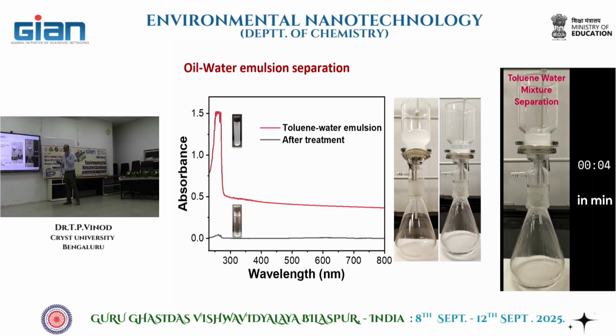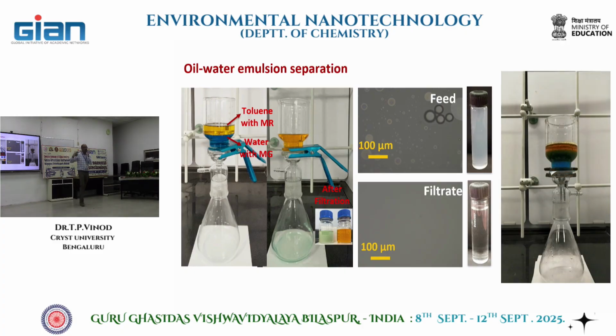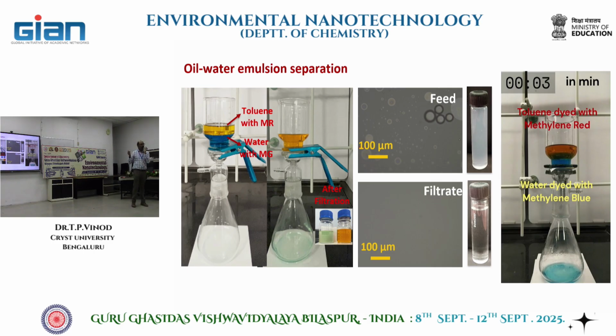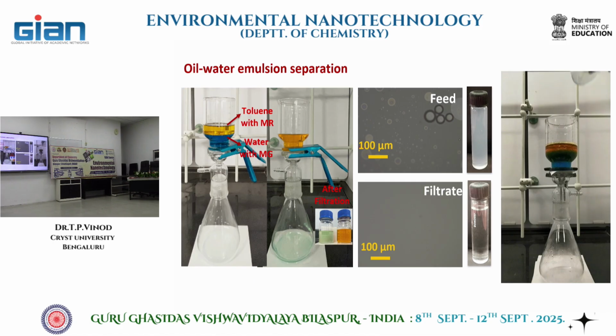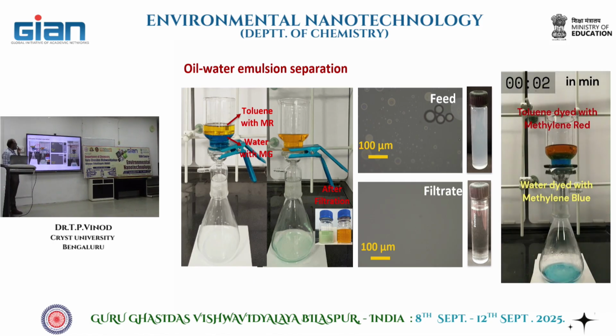Okay, so then what we did was, I think I have a better video here. So we made a oil-water mixture, which is actually a mixture of toluene, and toluene is dyed with methyl red, an orange-colored dye. And then water is mixed with methylene blue, okay? And then this mixture is poured over here, and then it was just kept there for some time. You can see what happens. We are pouring, and the time is shown at the top. Yeah, so it's totally separating with each other, even without application of any pressure.